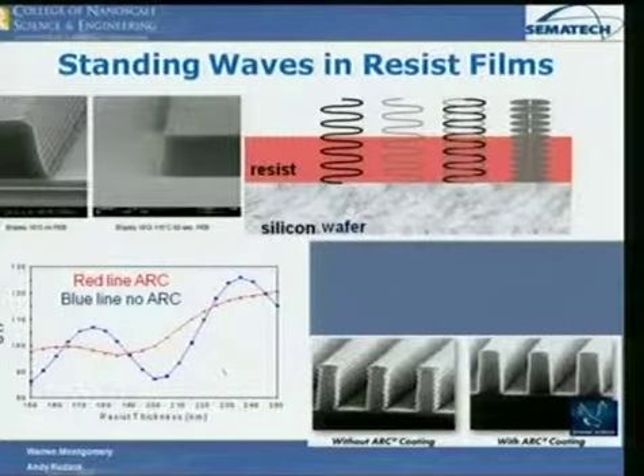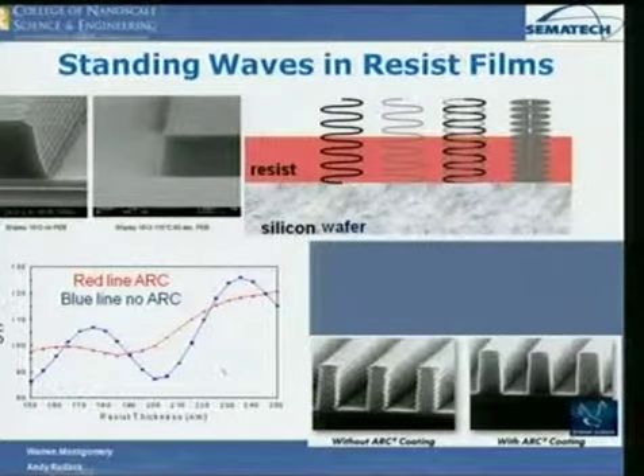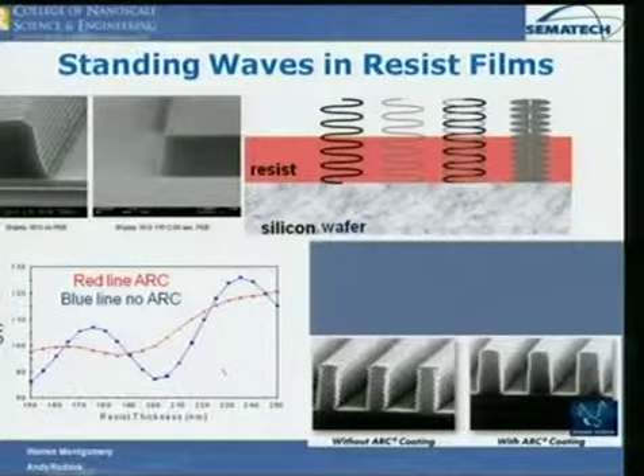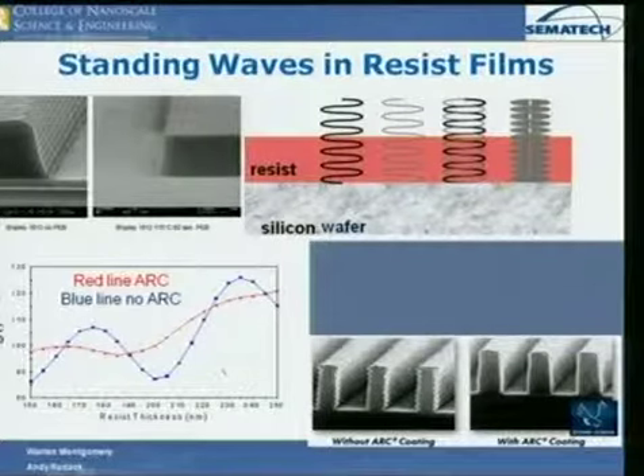Another solution was those bottom anti-reflective coatings I told you about, which we show here. Here's the standing wave phenomenon. This is with bottom anti-reflective coating on it, and notice we don't get those. And we didn't have to do the higher bake. So the standing wave was caused by this effect.